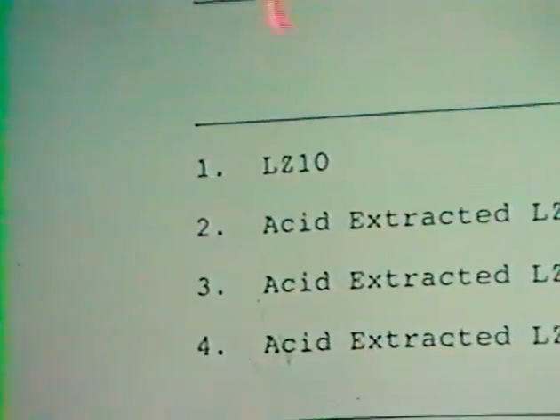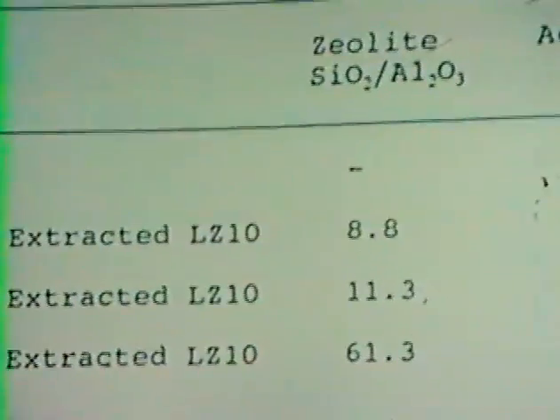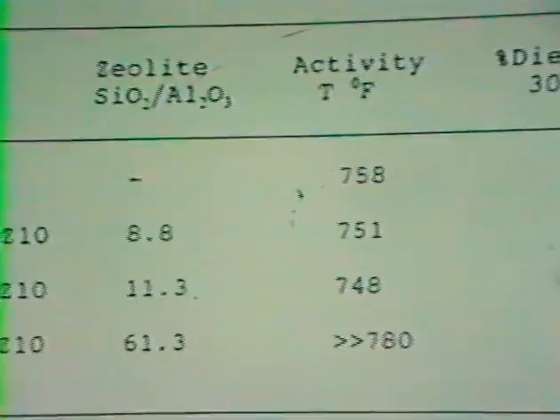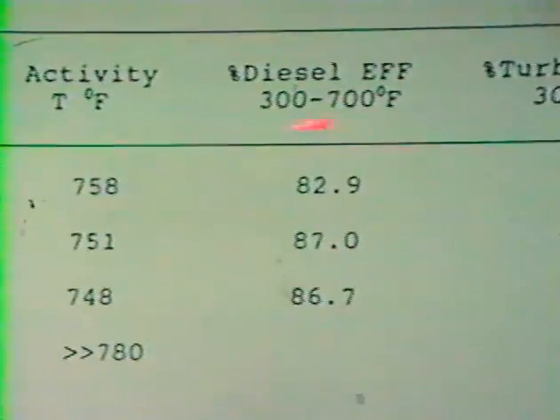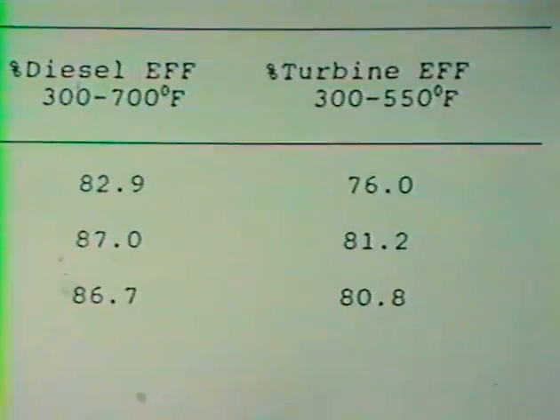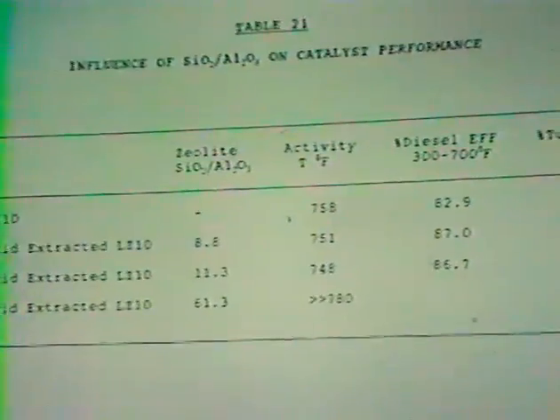Here's what happens when one treats an LZ10 catalyst, which is a double steamed Y zeolite, with acid. The nominal silica to alumina ratio would be about 5.6. We get an activity of 760 degrees, and the selectivity to diesel fuel of 83%. We remove the alumina out of that by acid extraction. You can see that we go to a ratio of 8 or 11, we improve the activity by 10 degrees or so, and significantly, 5%, increase the selectivity.